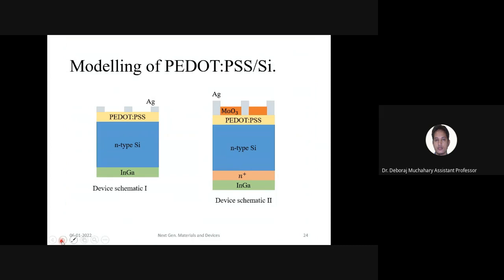Now the modeling of PEDOT:PSS. I have taken this simple model. You can take PEDOT:PSS, n-type silicon, indium gallium, and you can use a back surface field layer, an n-plus layer, so that the recombination at this back interface will be less. And one MoO3 layer, if you are using, that is anti-reflection. Anti-reflection means the reflection here will be less. So this type of techniques they have used.